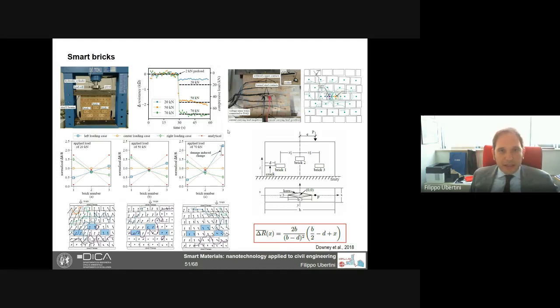On the top, you can see that if you apply a load, there is a change in the response of the brick. So in the sound conditions, we can actually track the load intensity. But if you look at the middle figures, you see the normalized change in electrical resistance of each single brick divided by what we read at the mid brick. So essentially we divide the output of the 3 bricks with respect to the output of the middle brick.